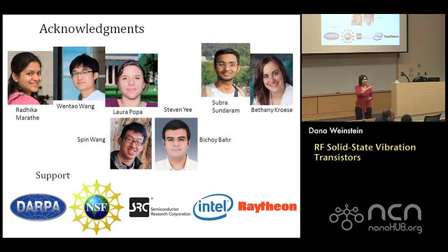What's the expectation about the power handling of this kind of resonator? As I mentioned, for the power handling in electrostatic devices, you're limited to essentially breakdown of the dielectric. So whatever fields you can get across your dielectric without leaking. In gallium nitride, it's over 30 dBm as measured now, and limited by self-heating. Those measurements were done at Michigan. Mina Rais-Zadeh has a GaN resonator showing that.